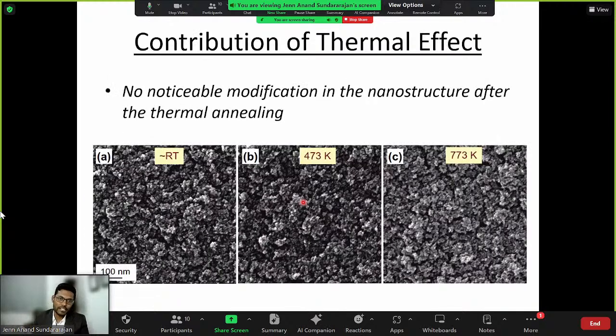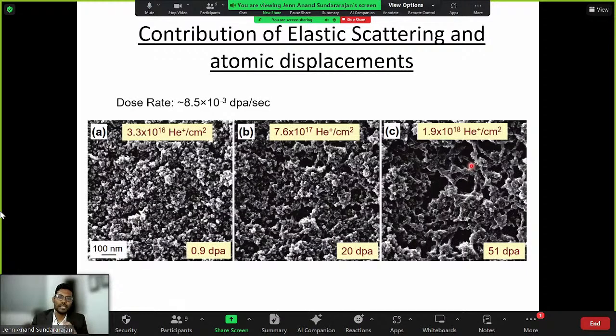What about the thermal effect? Because you mentioned that there is temperature, there's going to be diffusion, there's going to be agglomeration, coalescence of voids and stuff. What about the thermal effect? If you purely expose to thermal, there is no change actually happening, because even up to 773 Kelvin there is no agglomeration or change in physical properties of these nanoparticles. The only time any agglomeration or magnetic interaction starts to kick in is when we irradiated with heavy ions. We started with the helium ion, the lowest and lightest ion here, and we can start to see it change structure and so on.